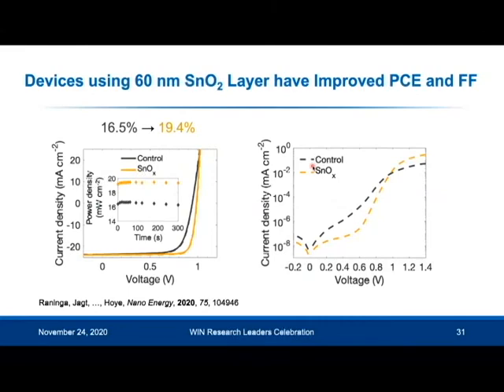And we optimized the thickness of the tin oxide buffer layer with the triple cation devices, and here we used more reflective aluminium top electrodes, and we were able to improve the efficiency from 16.5% to 19.4%, and the improvements came about through this increase in the fill factor up to a value of 84%. So this is quite a good improvement, and the reason for that is again because the PCBM layer has some pinholes, which leads to a low shunt resistance, and when we grow the dense tin oxide layer over it, we block these shunt pathways and we reduce the reverse bias current density.